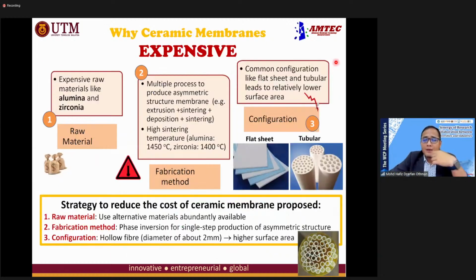Okay, when I mentioned that ceramic membrane is expensive, this is the reason. Firstly, the raw materials of the ceramic membrane, alumina and zirconia, are much more expensive than the polymeric material. It is probably more than 10 times more expensive. And the fabrication method to produce ceramic membrane is a multiple-step process, which is very tedious in order to produce an asymmetric structure. As explained, we have to do extrusion, sintering, deposition, sintering, and repeat the method a few times in order to produce the desired pore size.